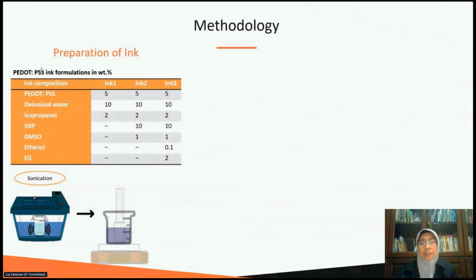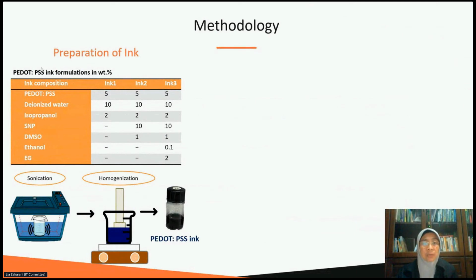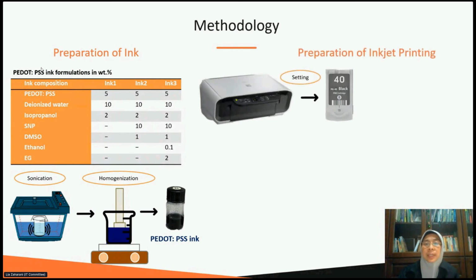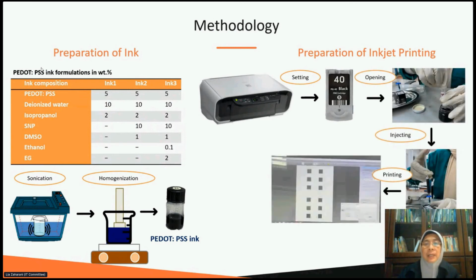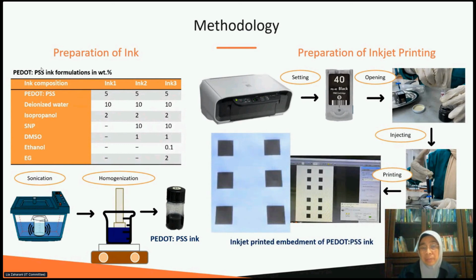So the methodology. We talk about the formulations. The content of each co-solvent, for example DMSO and ethanol, is obtained from the literature by choosing the one that researchers reported shows the optimum property, like the high conductivity that we are targeting. The SNP content is chosen based on our previous work, taking the ratio of 1 to 2 for PEDOT to PSS as well as SNP respectively. The content of IPA and deionized water is taken from the study reported by Soleimani-Jojani in a research article in 2018. The composite ink is prepared by the ultrasonic dispersion technique for depositing using drop-on-demand inkjet printing.